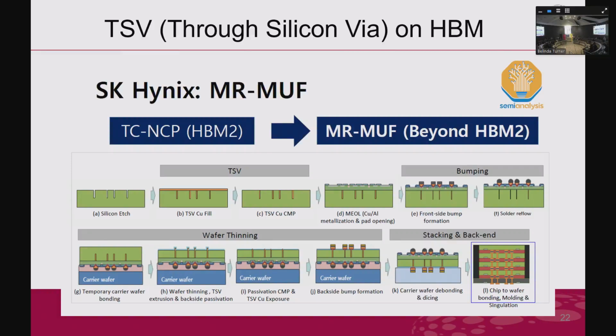And then you reveal the TSV, the deep groove. So that's why they flip over to finish the polish in the top layer to thin it, also by CMP process. Then you have that contact come out. As you come out, you also have to do that bumping to contact. So more like the beginning of the roll and the end of the roll.